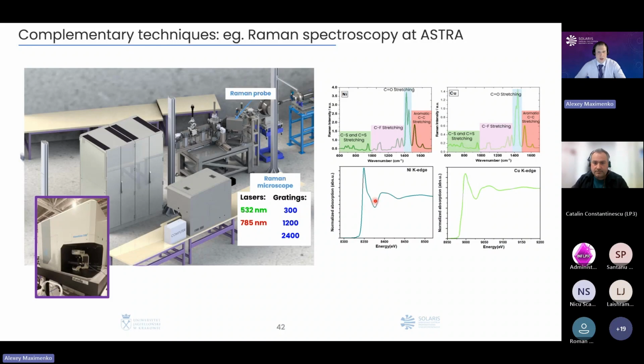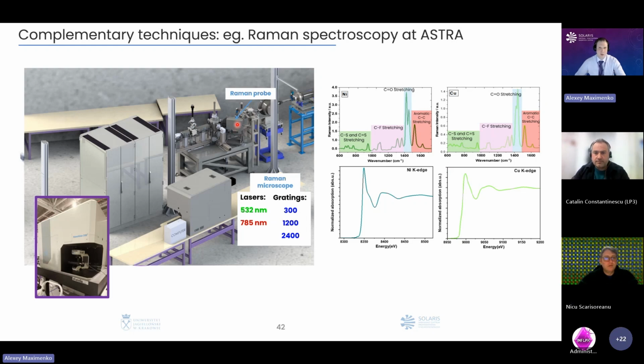And when we speak about X-ray absorption spectroscopy measurements, we are also used to make some complementary techniques. For example, during the same measurements, when you are getting XANES spectra, as shown here, you could have a probe from an FTIR spectrometer, or from a Raman spectrometer, or you can make XRD simultaneously on your sample if it is crystalline. In this example, I'm showing what kind of XAS spectra we could get, and also simultaneously we are measuring Raman spectroscopy, and in such a way we are getting information about electronic structure, local atomic structure, and also vibrational structure of our material during different reactions and different in situ experiments.